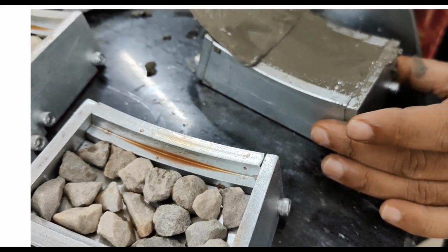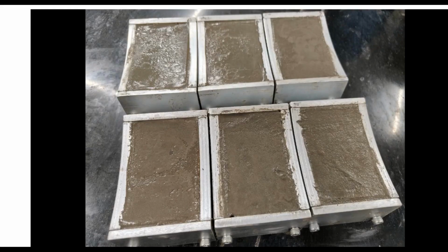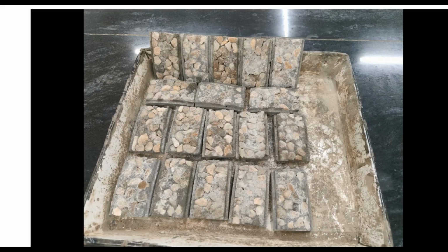And these samples can be taken out from the mold after 48 hours and then cured in water for 14 days to allow the cement to gain the strength. And that is how these samples with cement sand paste will look like.